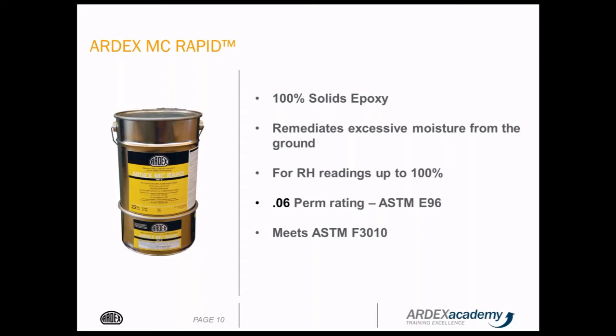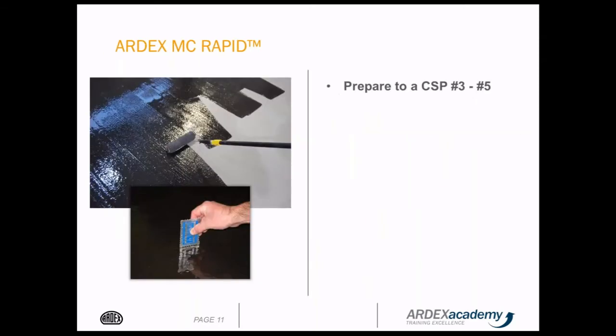ASTM F3010, the specification and standard for epoxy moisture remediation materials, states that the maximum perm rating would be 0.1, similar to that of the vapor retarder underneath the slab. We're pleased to report that MC Rapid has a perm rating of 0.06.